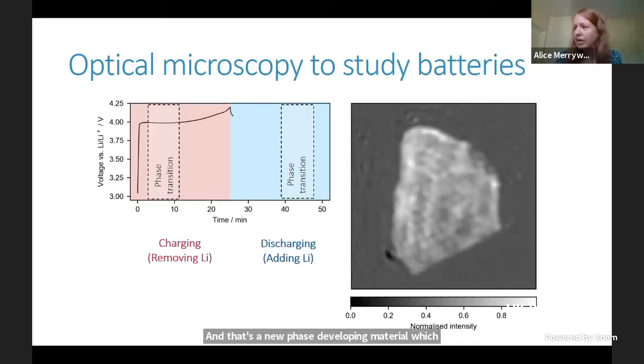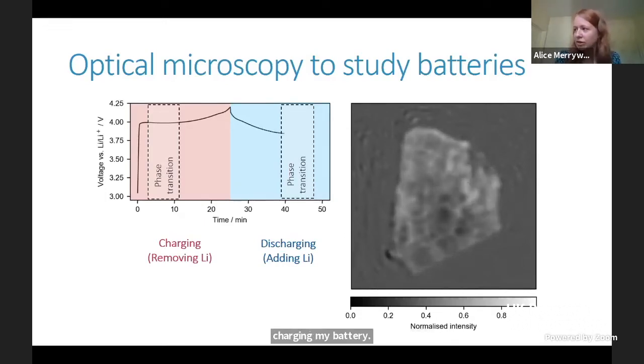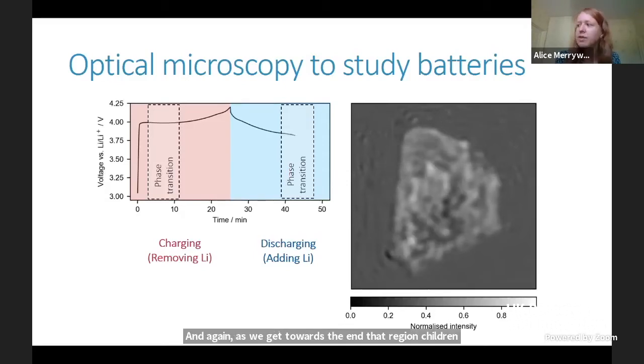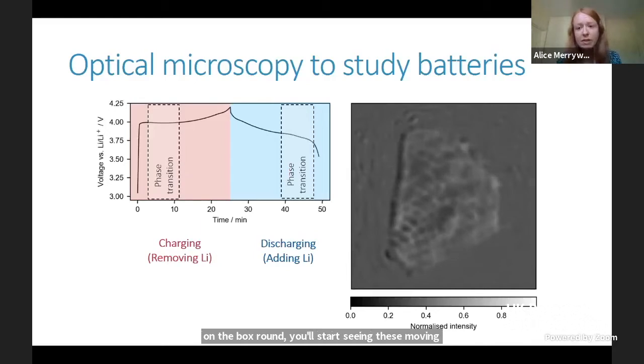And now halfway, I'm going to start adding lithium back in again. So now I'm discharging my battery. And again, as we get towards the end, that region which I've drawn a box around, you'll start seeing things moving across the particle. And again, that's a new phase containing lots of lithium ions moving back across the particle to fill it back up with lithium again. So I know that was quite quick to see, but we can get quite a lot of information about the different processes going on from a video like that.